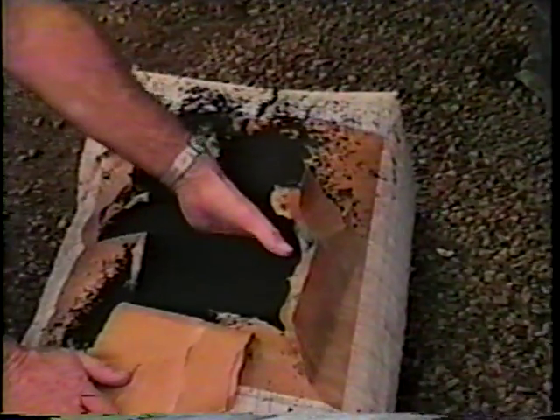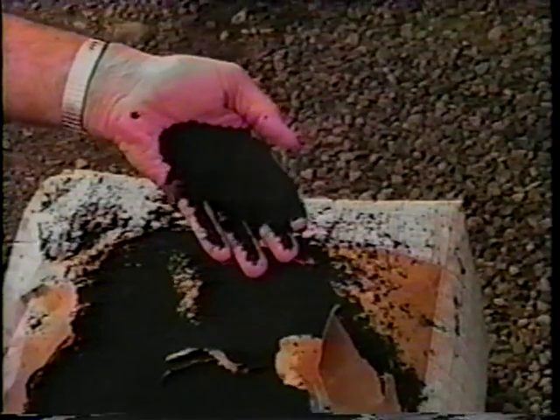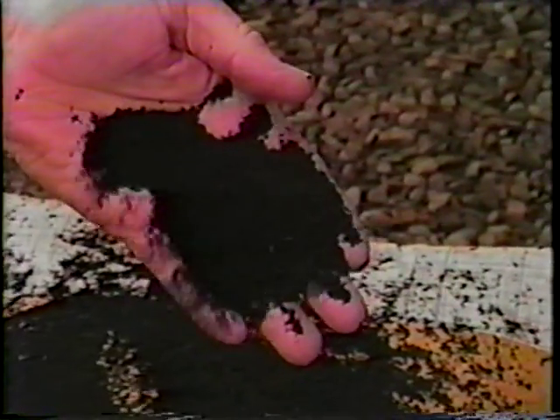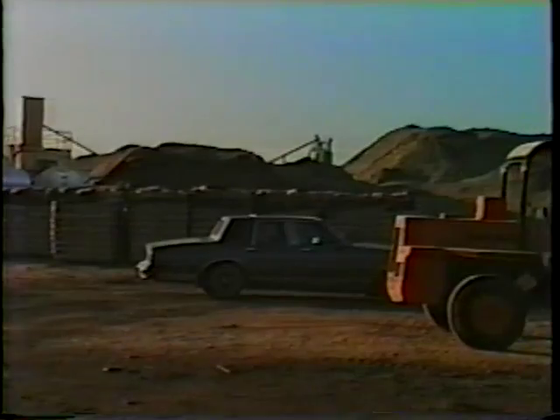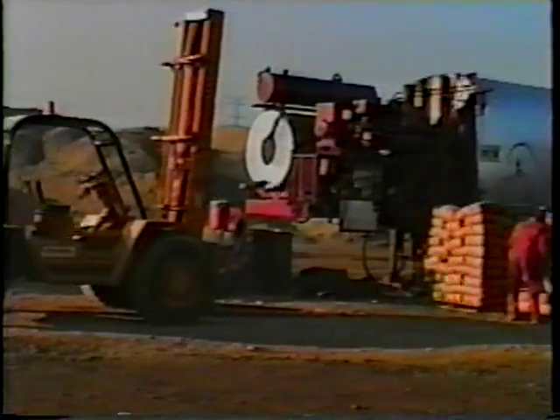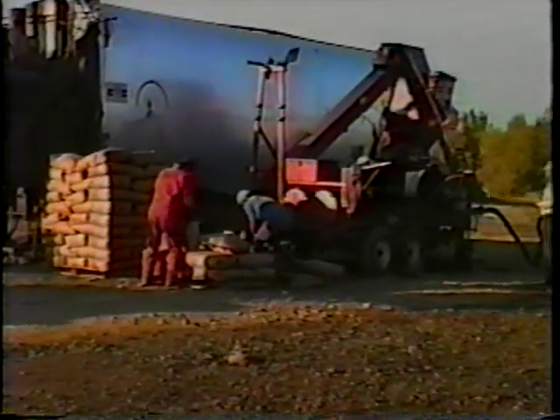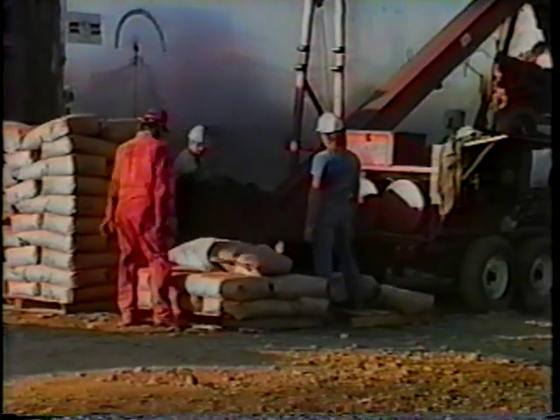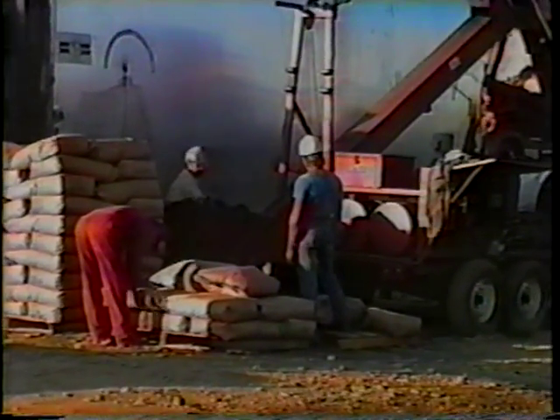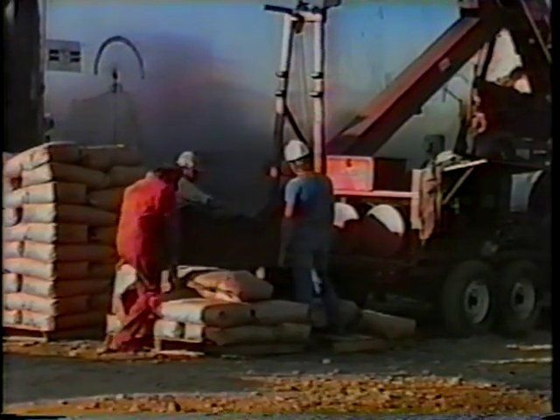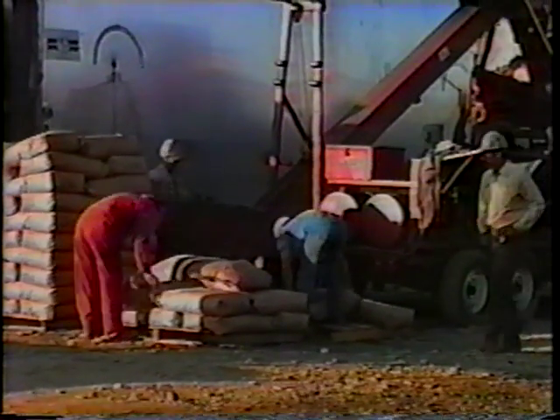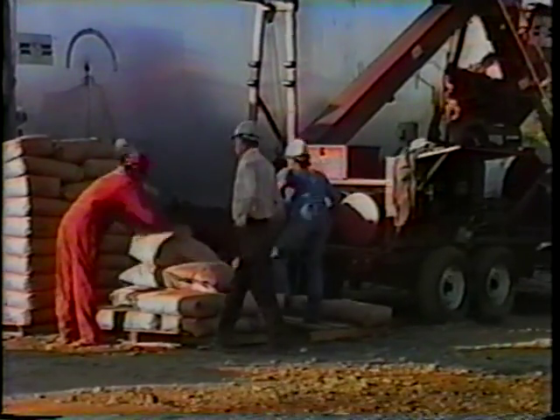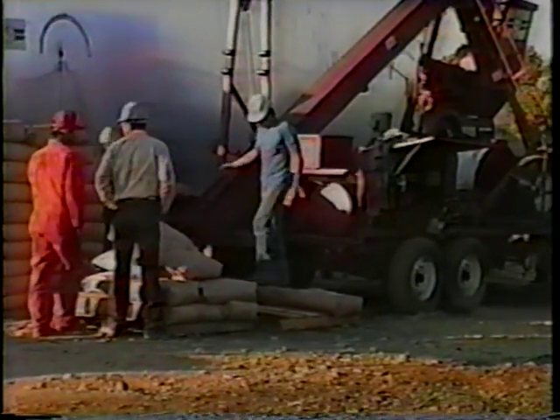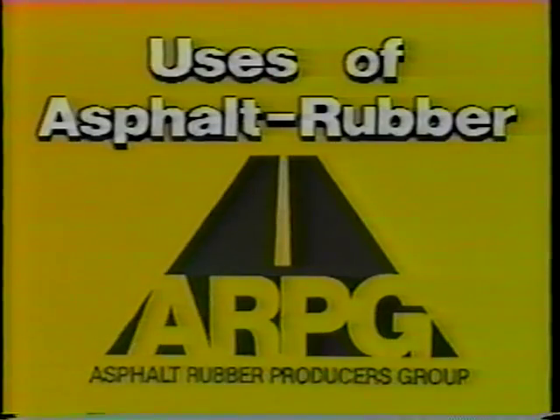The scrap rubber is ground or granulated into crumb rubber, shipped to a project site, and blended with asphalt cement. The blending process consists of mixing asphalt cement and 15 to 25% crumb rubber at 350 to 450 degrees Fahrenheit. This mixture reacts and forms a gel called asphalt rubber. Additives may then be incorporated to adjust the viscosity of the mixture. There are many uses of asphalt rubber.